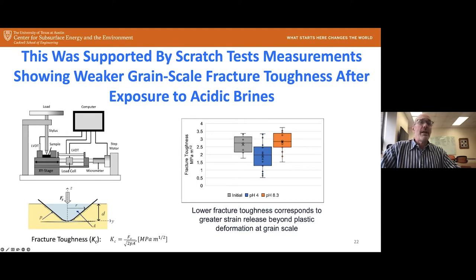And then what we do is we move the sample laterally so this stylus is dragged across the surface and we measure that lateral force. And that lateral force is this F sub T, right? P is just the perimeter length around that stylus and A is the projected area of the stylus at that point where it sinks down into the sample. So we can calculate our fracture toughness, and you could think about it as basically how much force does it take to dislodge grains from the surface of this material.